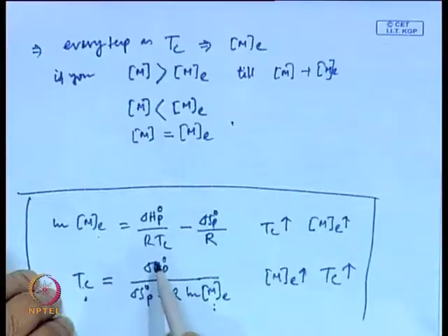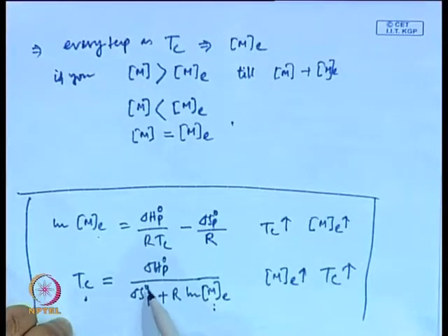Now, you can consider each reaction temperature as a ceiling temperature, and the equilibrium value of the free monomer concentration at that temperature is determined by the values of DelH and DelSP. So, the reaction at that temperature will continue till the free monomer concentration reaches the equilibrium value related to that temperature.